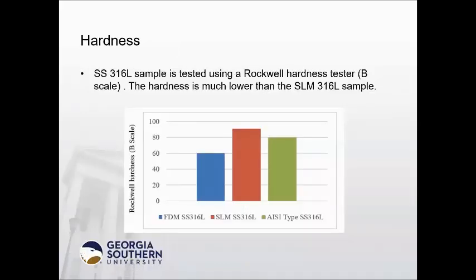And for the hardness, I use a Rockwell hardness tester, B scale, to measure the FDM stainless steel 316L, in comparison with selective laser melting stainless steel 316 and the AISI type stainless steel 316L, and the value is about 60. It is less than the SLM stainless steel 316L, because the SLM part has a higher dislocation density. So the hardness is much higher than the FDM stainless steel 316.